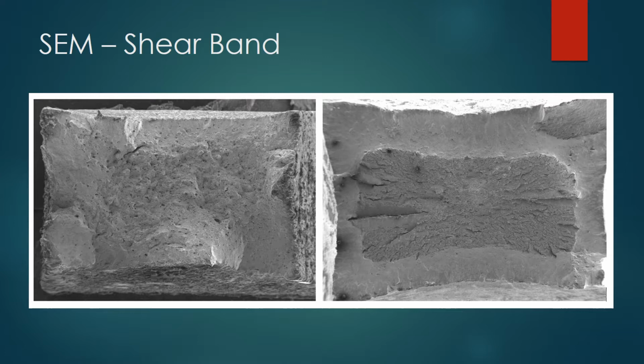And so the first images here, the one on the left is of the printed sample, and the one on the right is of the machine sample. The one on the right, you can see a very definite shear band, and then you can see a lot of the radial lines that propagate out, which is very characteristic of a ductile fracture. And on the left, there's not much of a shear band, and it's not very characteristic of what a ductile fracture looks like, but it also isn't very characteristic of what a brittle fracture looks like either. It's pretty jagged and sort of uneven and different than what most materials are characterized as.